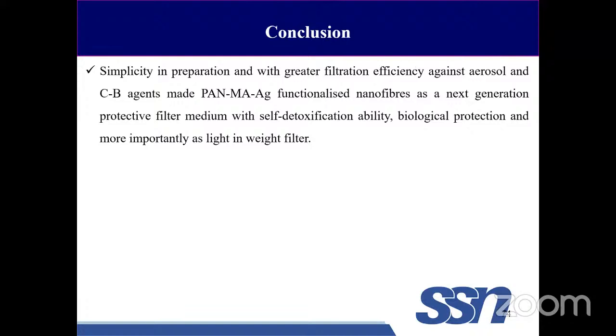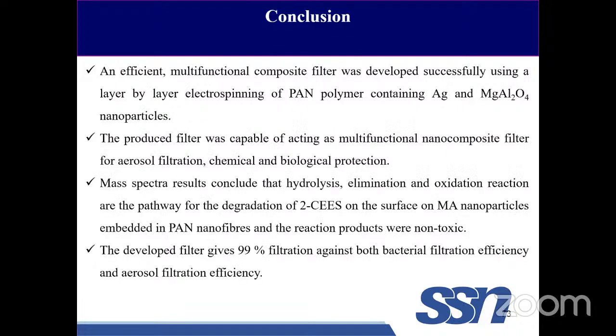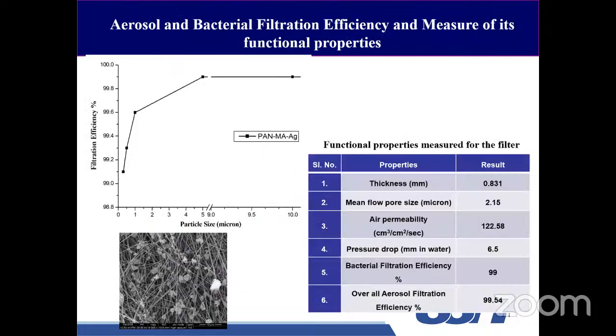And to conclude, it is a simpler technique. By utilizing a simpler process, we have prepared a multifunctional filter which is going to act against all 3 agents, that is aerosol, bacterial, and chemical agents, and it is going to detoxify these agents. More importantly, these are lightweight filters. As you can clearly see, the thickness is only 0.831 mm. The GSM is only around 40 GSM, so it is lighter than an A4 sheet of paper.